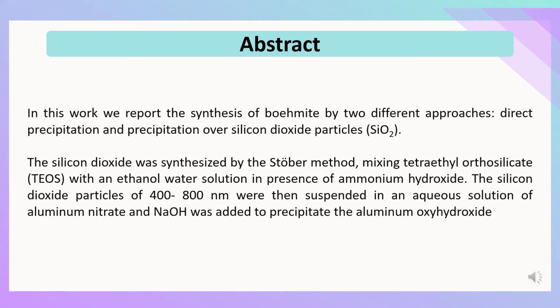In this work, we report the synthesis of boehmite by two different approaches. One is direct precipitation, and the other is precipitation over silicon dioxide particles. The silicon dioxide was synthesized by the Stöber method, mixing tetraethyl orthosilicate with an ethanol water solution in the presence of ammonium hydroxide. The silicon dioxide particles of 400 to 800 nanometers were dispersed in an aqueous solution of aluminum nitrate, and sodium hydroxide was added to precipitate the aluminum oxyhydroxide.